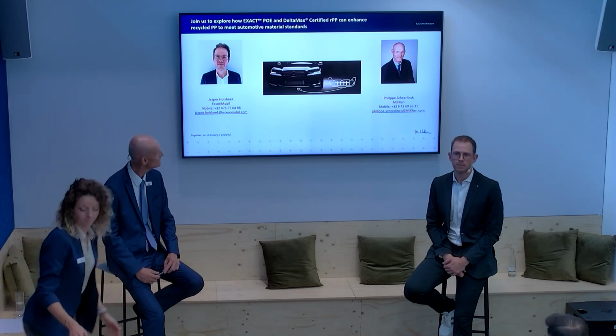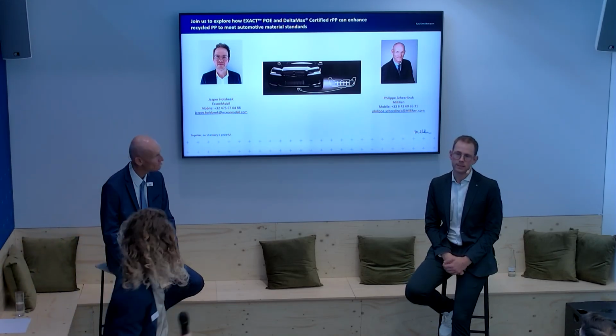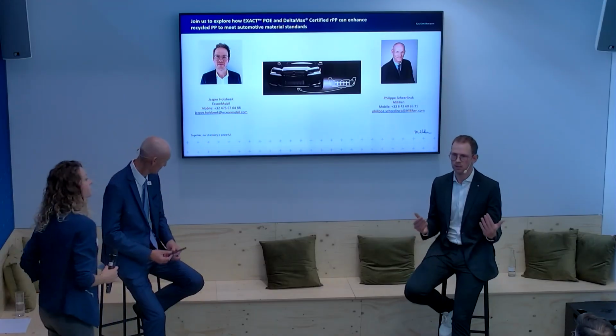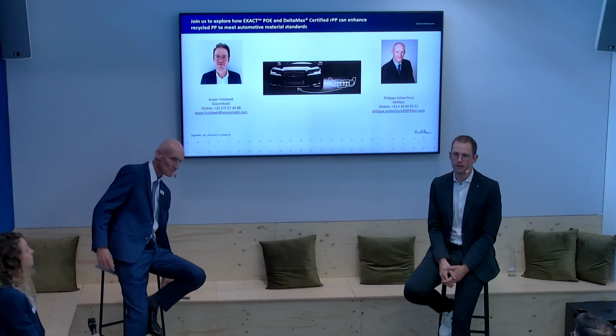Perfect. I can take that because indeed there is always a trade-off in properties. When you start blending performance material modifiers into any kind of stream, be it recycled or virgin material, there is always a trade-off between properties. In this case, you add more rubber content, really a lot, 20-25%. So that means that the impact performance comes from somewhere, and that's really the rubbery phase that you add. So the impact is really lifted, but the stiffness goes down.